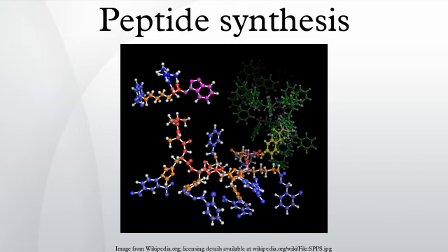PEG-based resin. ChemMatrix is a new type of resin which is based on PEG that is cross-linked. ChemMatrix has claimed a high chemical and thermal stability and has shown higher degrees of swelling in acetonitrile, dichloromethane, DMF, N-methylpyrrolidone, TFA and water compared to the polystyrene-based resins. ChemMatrix has shown significant improvements to the synthesis of hydrophobic sequences. ChemMatrix may be useful for the synthesis of difficult and long peptides.